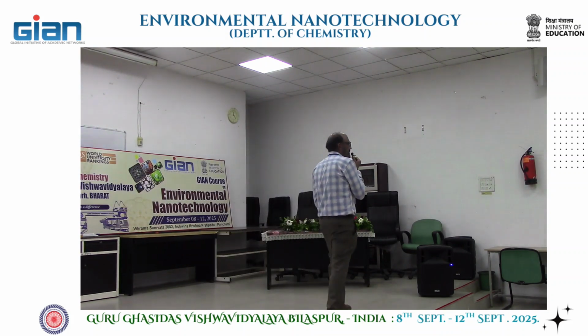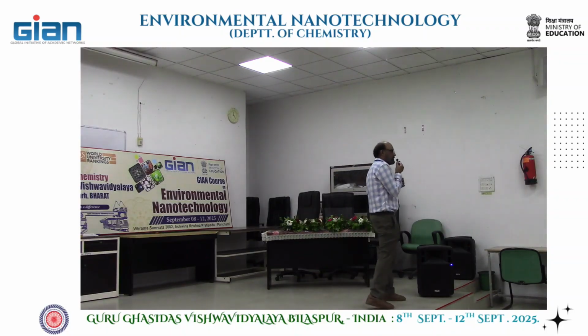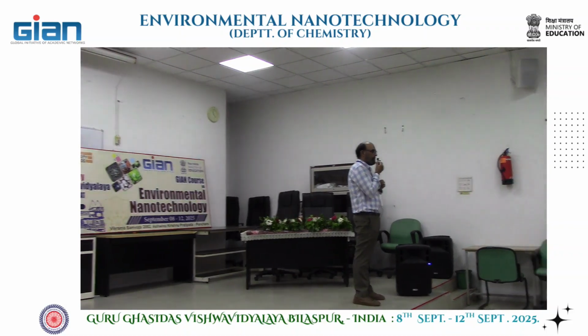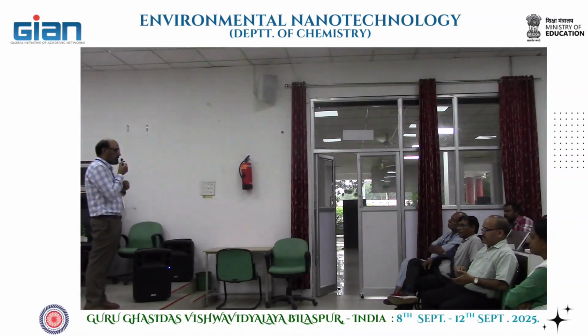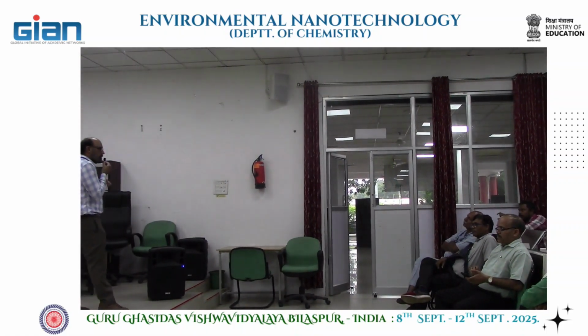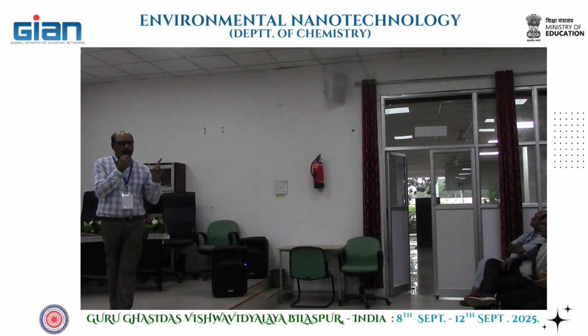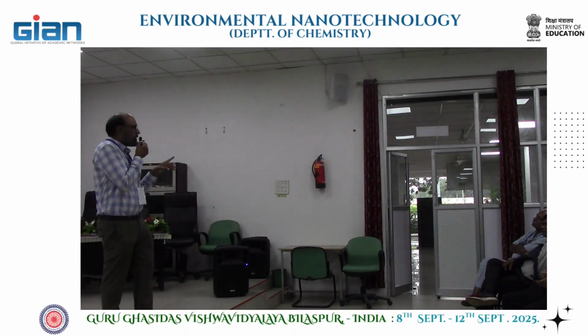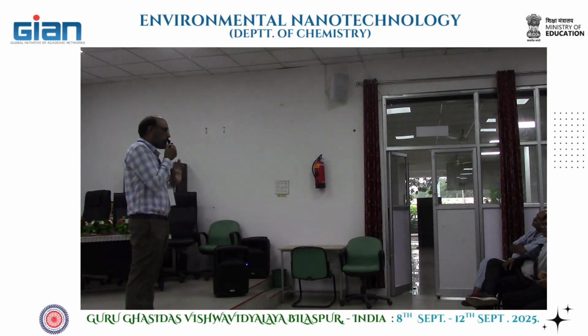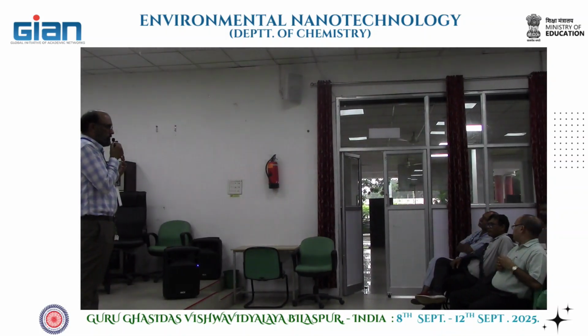Sir, very nice. I think these materials are very emerging and new. In this case, you are mixing polymer with some nanoparticles. What is the role of these nanoparticles and how is it done? We wanted photocatalytic dye degradation. For that, zinc oxide was added. At the same time, we wanted antibacterial activity, so we used silver doped zinc oxide nanoparticles, based on the functions.